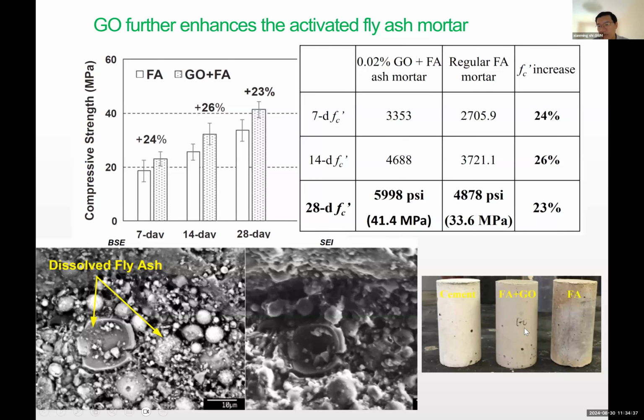But when you add graphene oxide, the one in the middle, you see the leaching stopped. So the surface is pretty smooth. This indicates that the 2D nanomaterial, the nanoplatelets we're talking about, has this wonderful ability to encapsulate the alkali. And this could be extended to encapsulation of heavy metal or other pollutants.